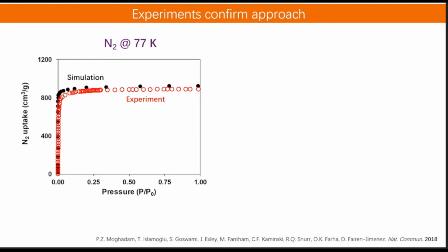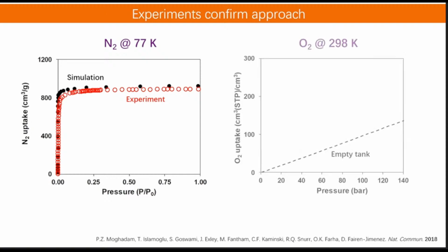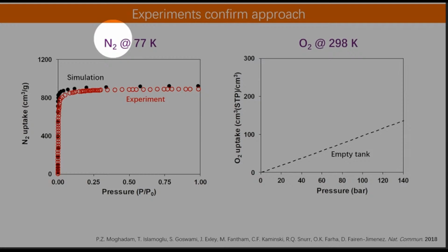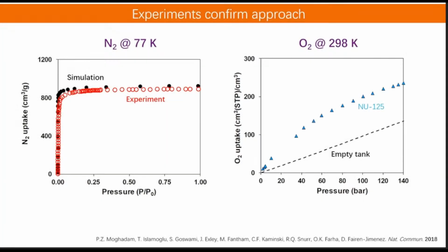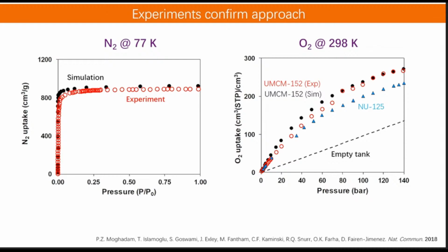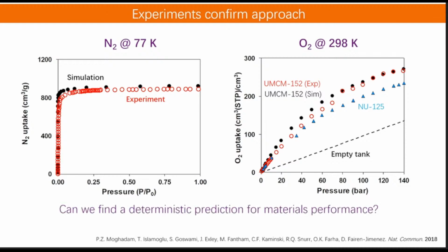And just to finalize these couple of ideas, yes, we can also confirm the fact that the simulations and experiments match each other, okay? The simulations are able to reproduce the experimental data properly. This is for the nitrogen isotherm, just to check the quality of the material, and this is for the oxygen at room temperature. This is the comparison with an empty tank. This is the best material that was published in the literature a few years before our paper. This is the best simulation we had, and this is the best material that we had in the experimental data, right? Very good match of experimental data, very, very happy with these properties.